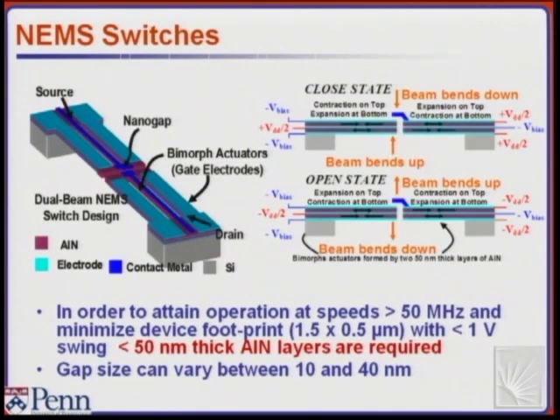And then we have a signal line that routes the signal, basically, and two gates placed on the left and right of the signal line that produce the actuation force. The problem is, we demonstrated at the MEMS scale that it works very well. Well, to go to the nanoscale, to produce those very small form factor devices with very low voltages, we need films now that are 50 nanometers or less. So that's a big challenge in scaling. And another challenge, which I think is less of a challenge than making the film thickness, is defining gaps that are now 10 to 40 nanometers in gap size, basically the air gap size.